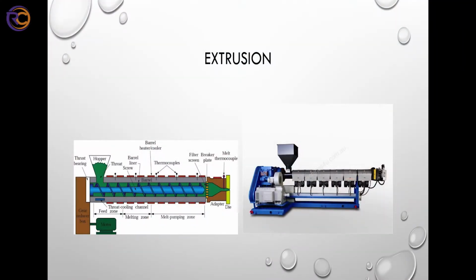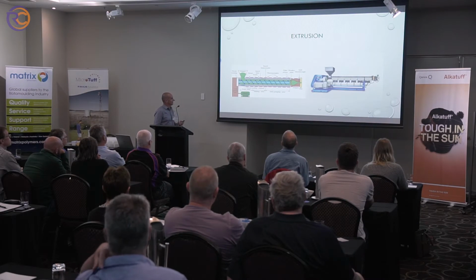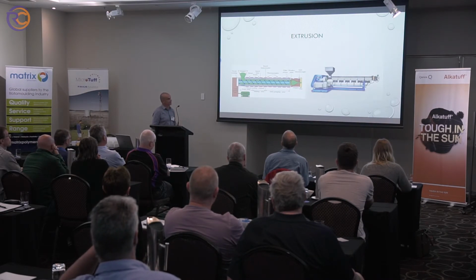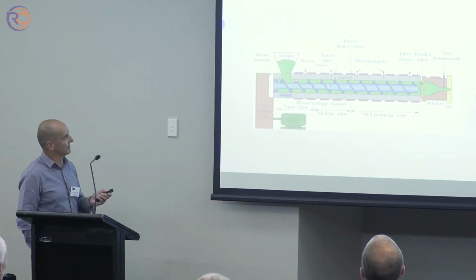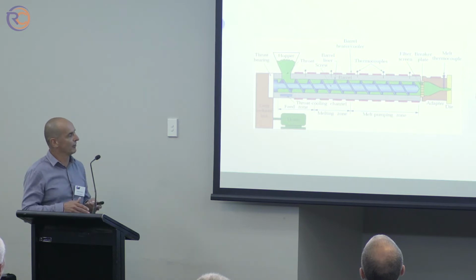So to talk a bit more about an extrusion line. This area here is the feed section or the hopper, and above that you would normally have a mixing station. The material goes into the extruder and travels along the extruder, and you can see the screw here, the diameter is a lot smaller here compared to here, and this is where the granule is starting to melt and being transitioned through, and you get to this stage here and it's compressed. So it's travelling up the barrel and compressing the material, and it's also helping to mix the product. And sometimes the material actually goes over the flights, and this also helps with the mixing process.